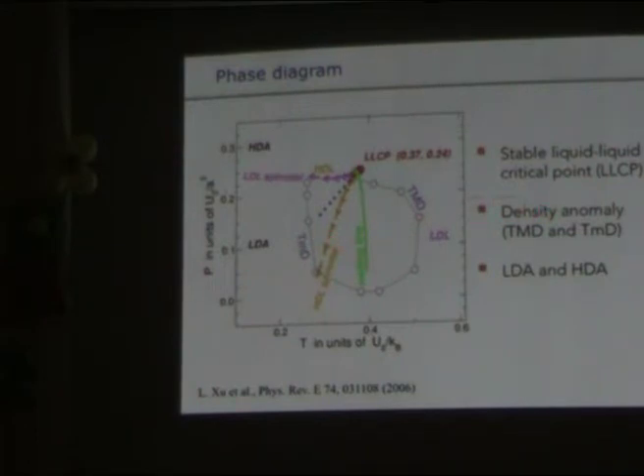And also we have other water-like anomalies, such as density maximum. So this is in the PT phase diagram. I just put all of the data right here. So this is the density maximum region. And we also have this density minimum region that was later observed by experiment. So you can see this is the density anomaly region. And we have this low density liquid, high density liquid, and low density amorphous, high density amorphous.